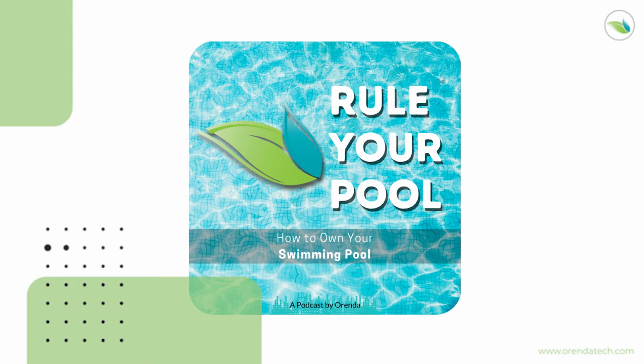And it may not be aggressive water that causes it, but On Balance is saying, look, it could be ground shifting. It could be a settling of the earth. It could be too slow of a pool fill, which actually agrees with the NPC that the hydration rate was inconsistent. Is inconsistent the right word? Let me think about that. Accelerated drying, maybe. On Balance would say you put too much calcium chloride in the mix. It accelerated this too fast, therefore it lost volume too fast. It set too quick. You didn't fill the pool up quick enough.